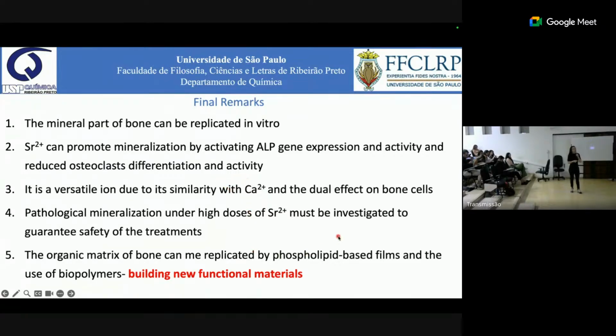but we also have to investigate possible side effects when we are using strontium. And we have studied this in the group. I'm not showing it here because of the time, but we have shown that increased collagen and strontium concentrations have bad effects on the structure of hydroxyapatite, and also disturb the organization of collagen. And increased concentration of strontium in the materials can also reduce the attachment of osteoblasts on the materials.